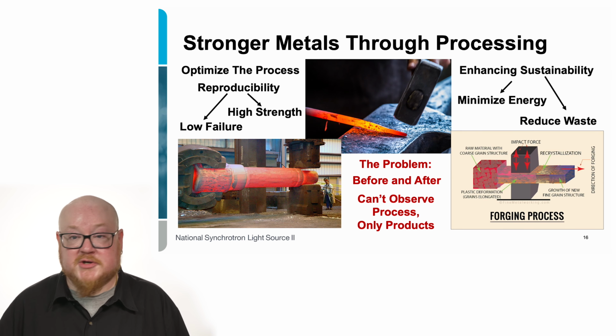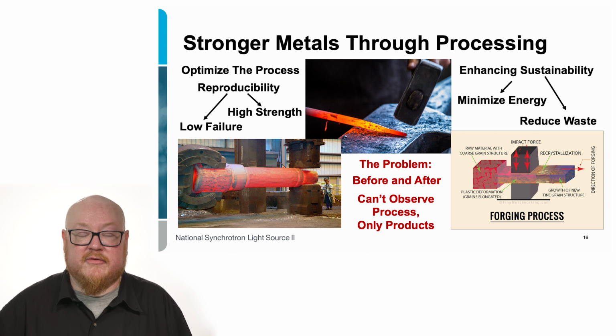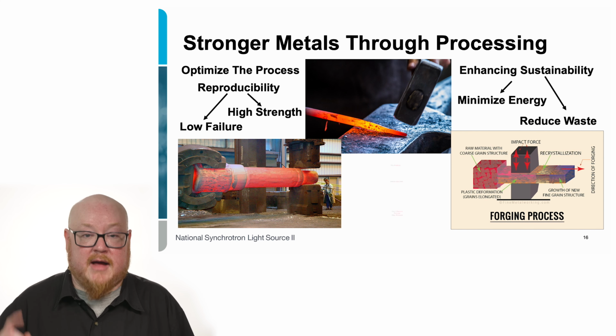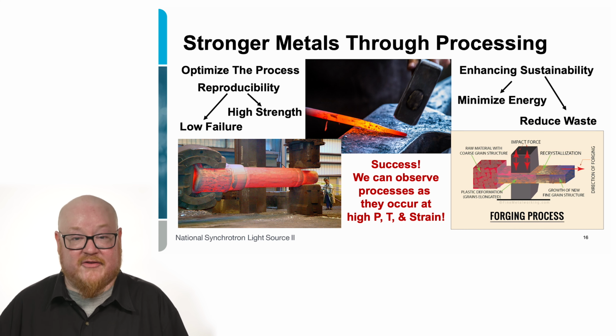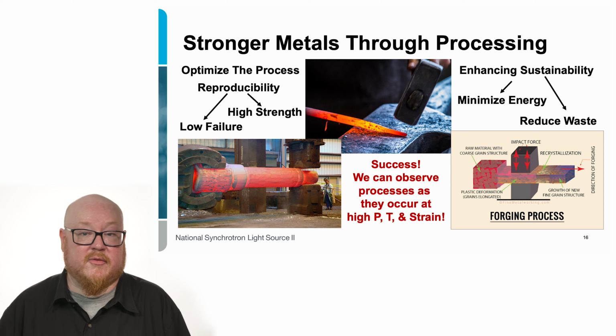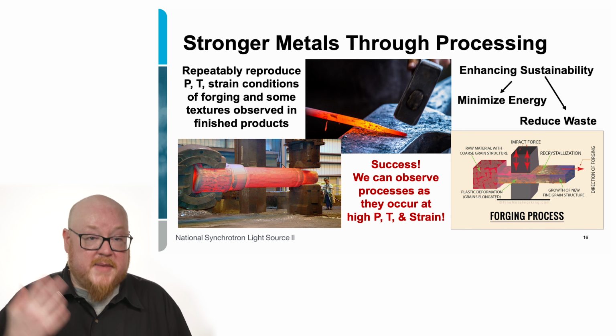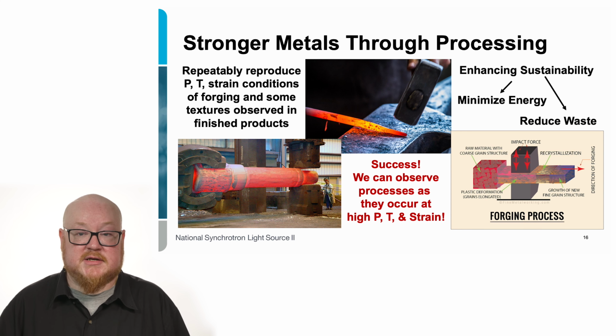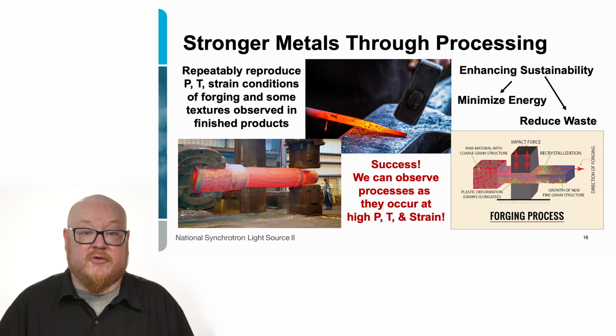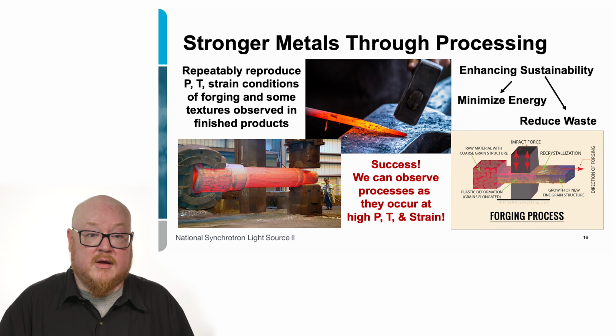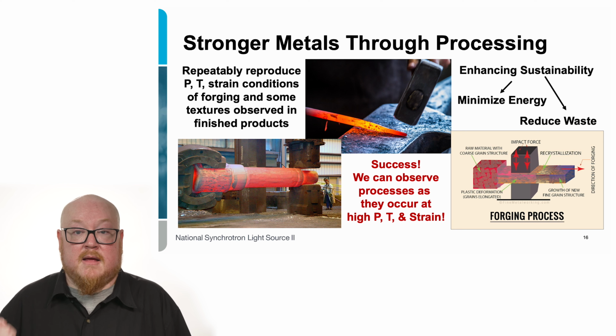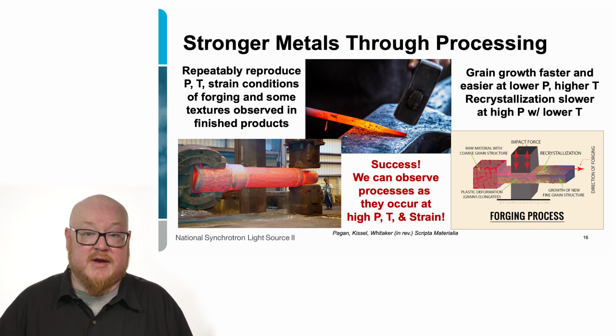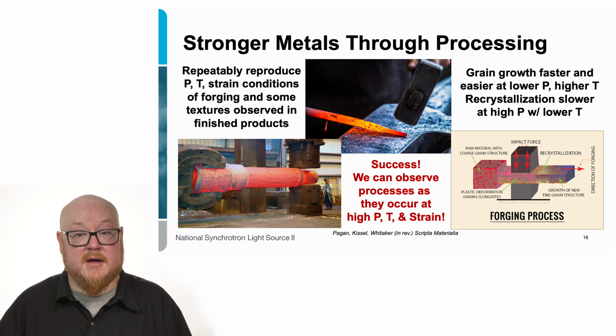So going back to the original reason for all of this, the problem: we couldn't see anything but before and after. And we have had success. We can observe these processes as they occur at high pressure, high temperature, and with directional strain. We can repeatedly reproduce these pressure, temperature, and strain conditions that are found in forging and some of the textures that we observe in the finished products in real life. So we know, based on what we're seeing afterwards, that we're able to replicate what's going on in these materials, which is really, really important. And we found that grain growth tends to be faster and easier at lower pressures and higher temperatures, and the recrystallization process is a bit slower at high pressure with lower temperature.